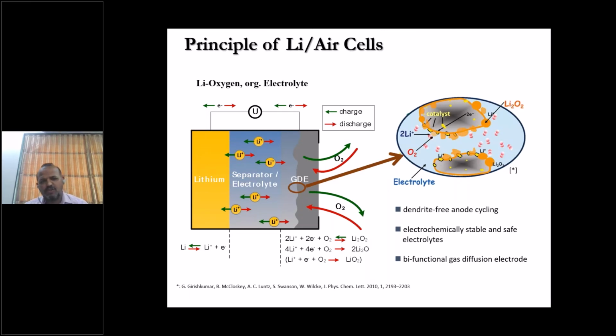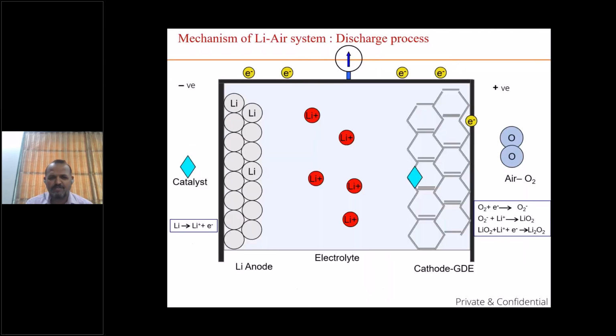Then one more new technology people are trying is the lithium oxygen battery, where there is lithium metal, then electrolyte separator and a gas diffusion electrode, which can take the oxygen from air and react, and it has an energy density close to oil, diesel and petrol energy density because of the oxygen and because of the high transport phenomenon. But in lithium oxygen batteries, there are still fundamental issues with whether it is safe, and it doesn't have a larger cycle life.